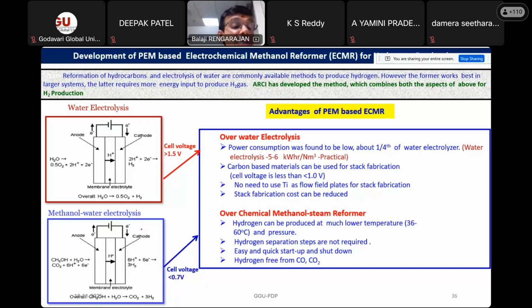And the advantage is that when you want to employ water electrolysis at 1.5 volt, you have to use some metal based material, because you cannot use any carbon based material for the stack construction, as the carbon will undergo oxidation in that particular potential range. Whereas in the case of methanol water electrolysis, we have reduced the operating cell voltage to close to 0.5 to 0.7 volt, and here you can use a carbon based material for the stack construction.